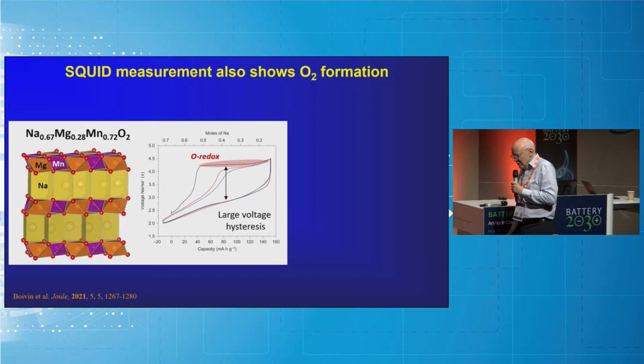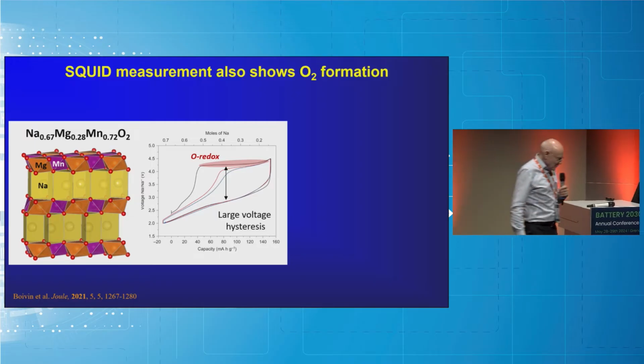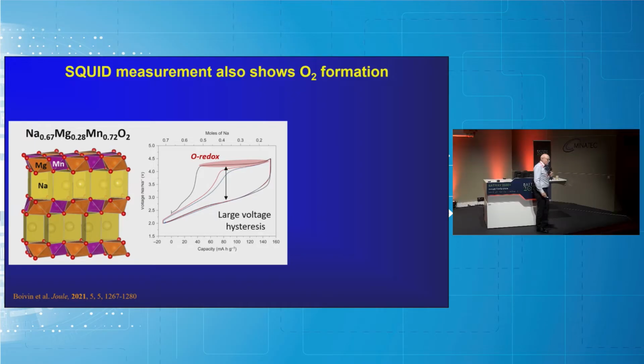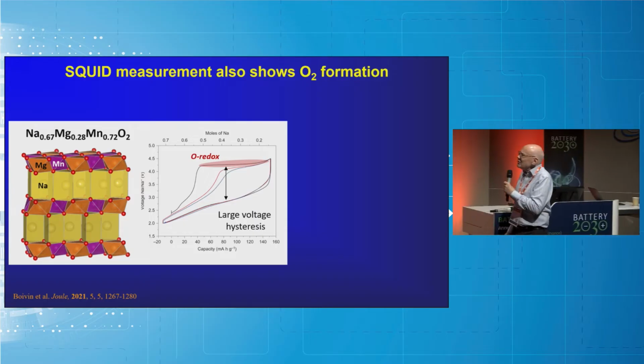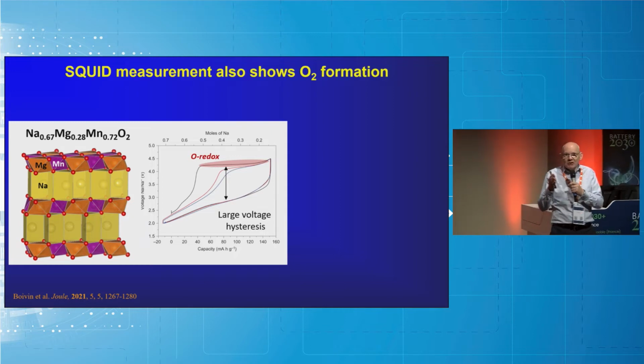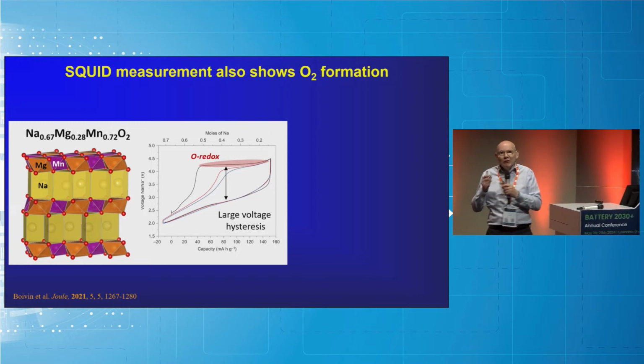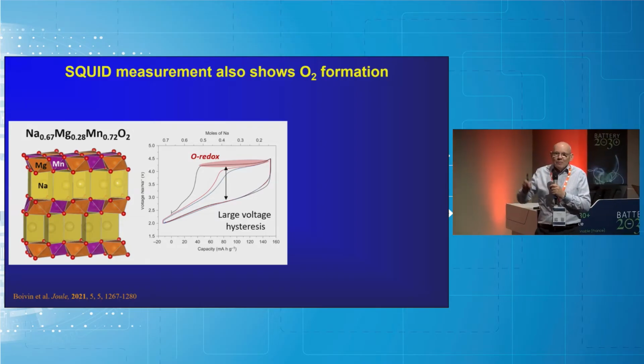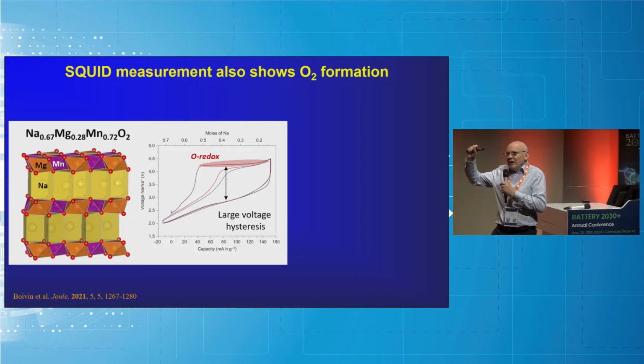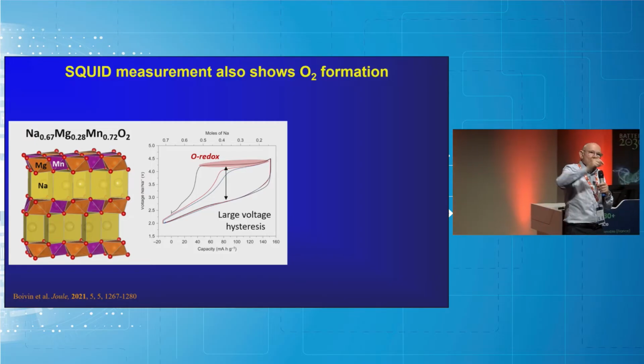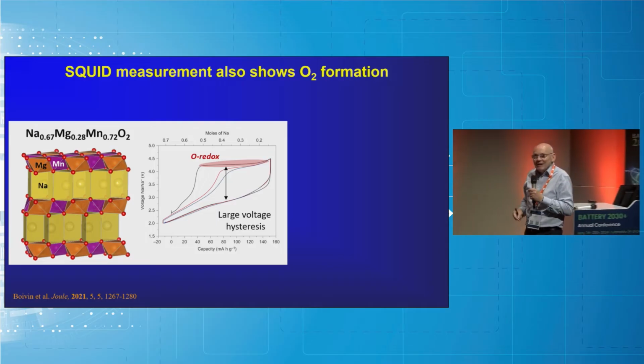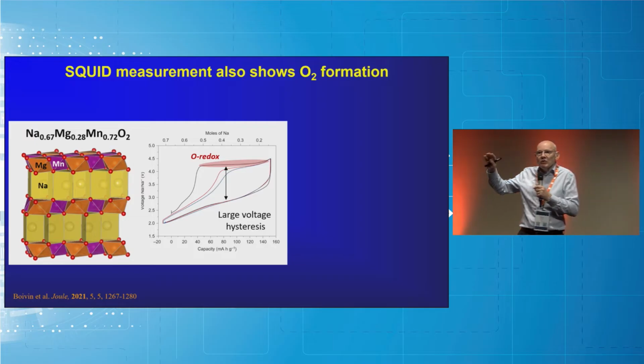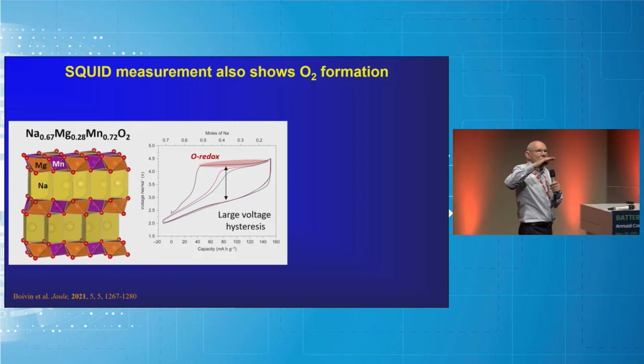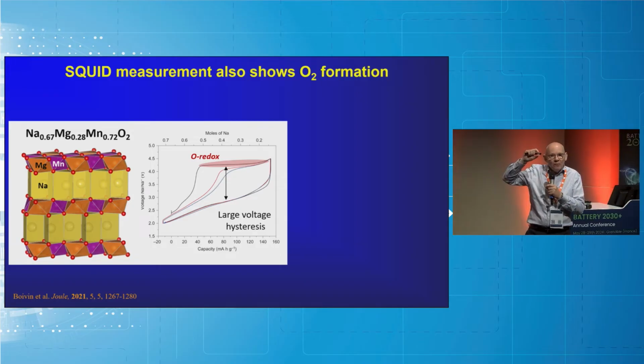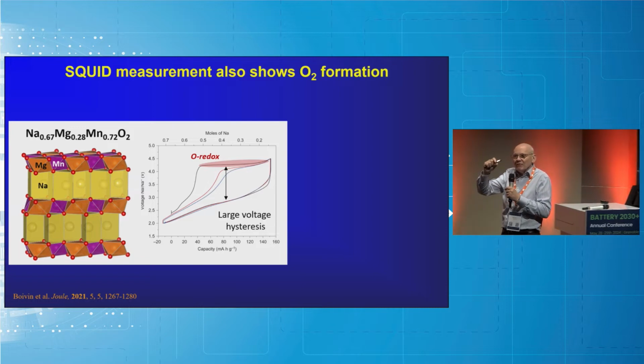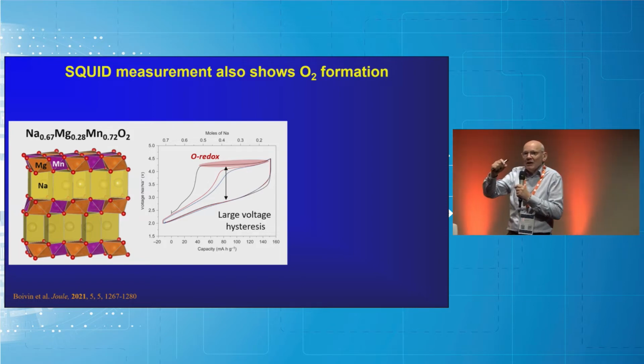And if you don't believe RIXS and you don't believe PDF, maybe you believe magnetism. So here's some SQUID measurements on a different material that also shows oxygen redox. It's very interesting. We started looking at this material. It's a sodium intercalation compound, but that doesn't matter. The reason we looked at this material initially was that, as I've already shown you, and as you know, in lithium-rich transition metal redox, you remove lithium ions. Some of those come from the transition metal layers, and in fact that's fundamental because, as I'll show you in a moment, those vacancies that are created in the transition metal layers reorganize to form voids to trap the O2. So that's fundamental to the formation of O2, or at least its trapping in the particles.